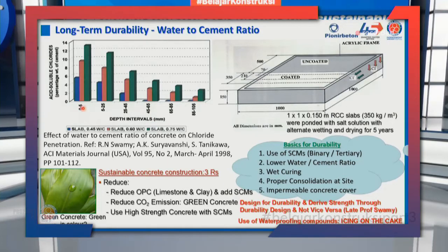You can see 0 to 5 is always weaker. 0 to 5 is the upper surface. It is subjected to bleeding. You always find more porosities. So don't worry about 0 to 5, but start looking from 5 to 25 onwards. If you go to 45 to 65, for water cement ratio of 0.45, there are absolutely no chlorides. For the other water cement ratios, 0.75 and 0.60, you still find chlorides at a depth of 85 to 105. That means if you use a lower water cement ratio, that's the best method to control the penetration of chlorides and sulfates.